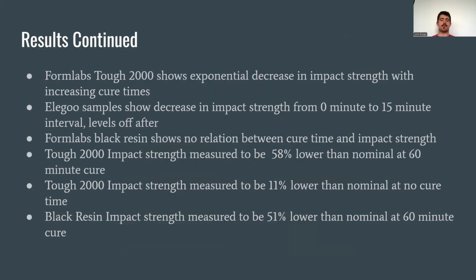The Tough 2000 had the most change with cure time, going from having a high impact resistance to a lower one with increased cure time. The Elegoo decreased initially but remained at about the same impact resistance after 15 minutes, and the black resin showed no relation to cure time with impact energy.